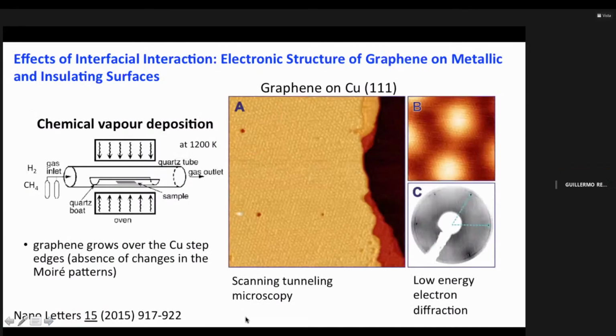So this is something that we did quite a few years ago. We showed that you can prepare graphene by chemical vapor deposition both on metallic surfaces, as most people do, and on insulating surfaces. And you see that the quality is